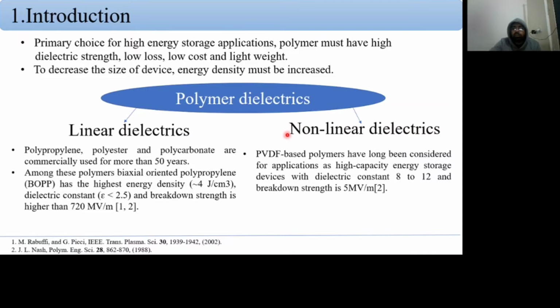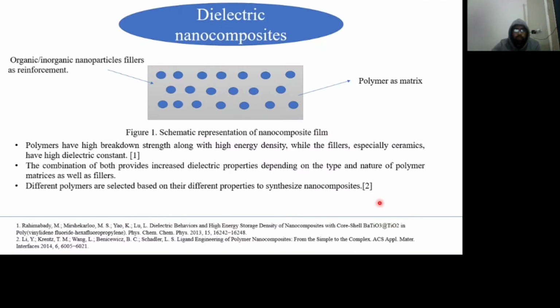Non-linear dielectrics are those dielectrics which have a polarization versus electric field plot as non-linear. PVDF is a famous polymer material which has a high energy storage capacity, and it has a dielectric constant of 8 to 12 and high dielectric breakdown strength.